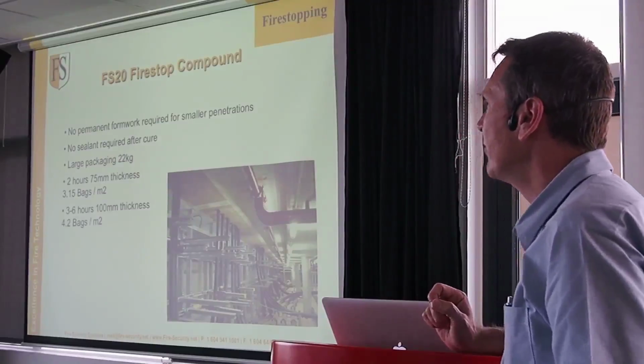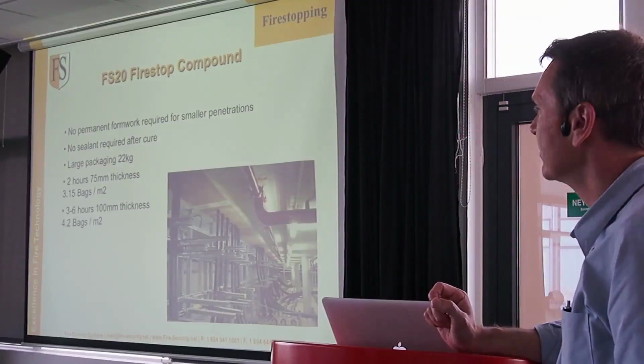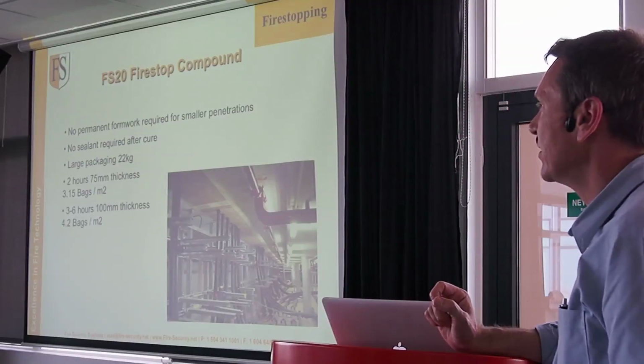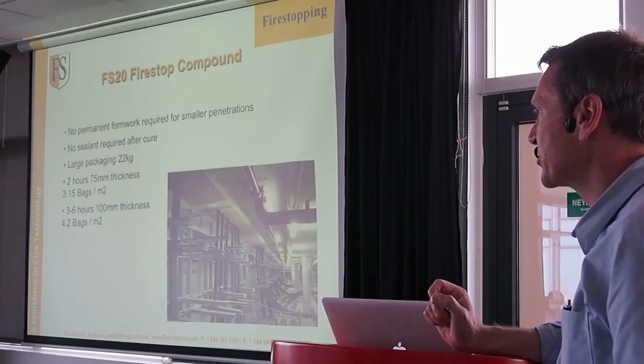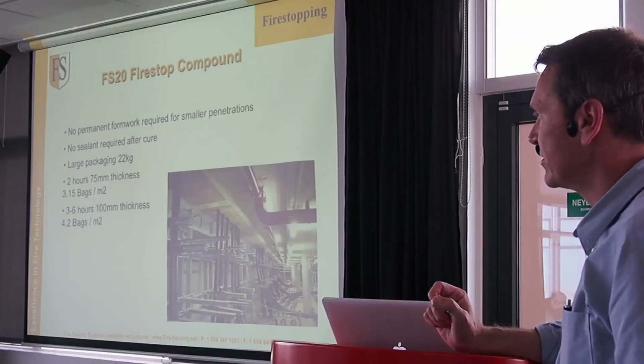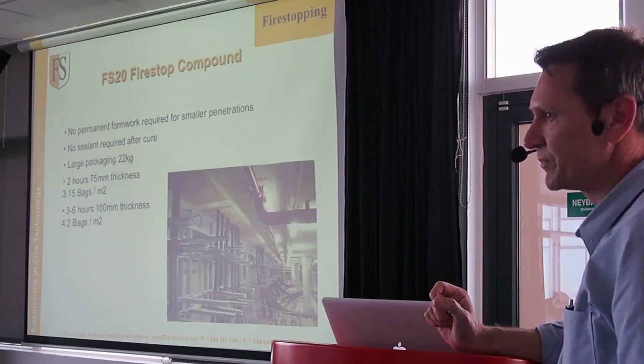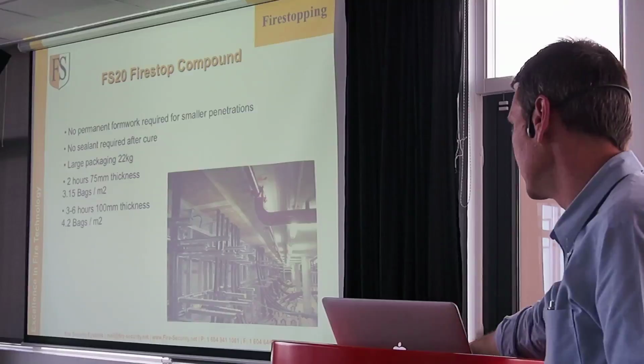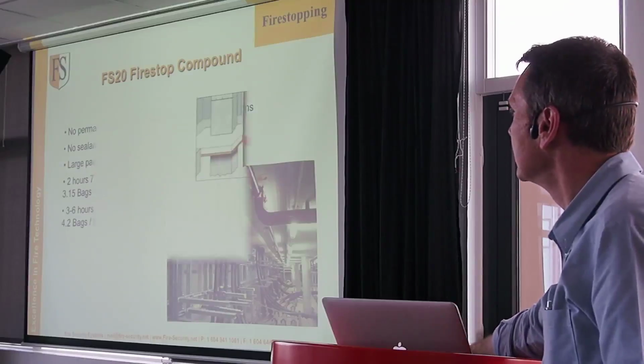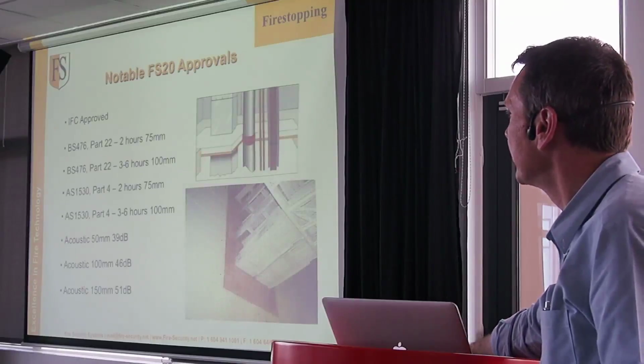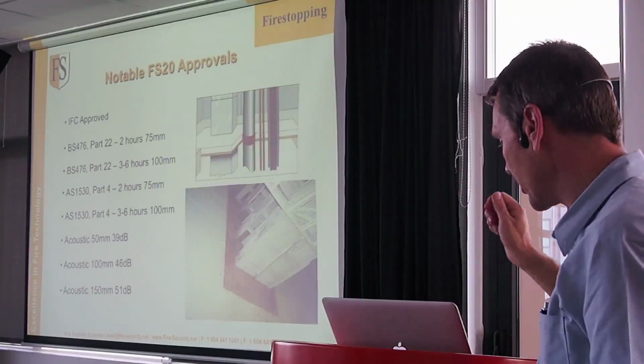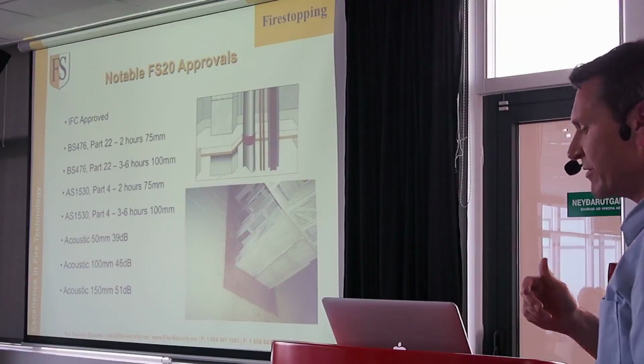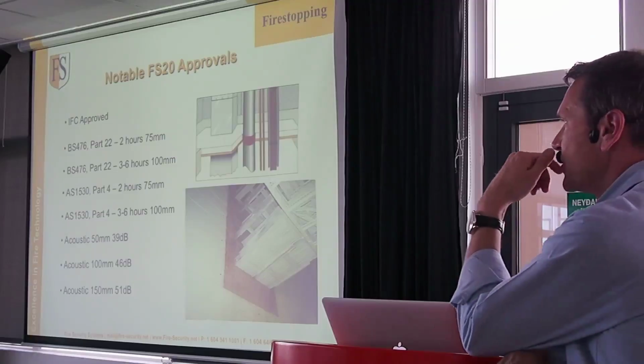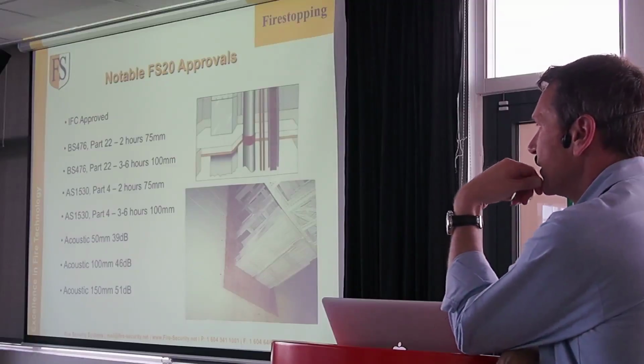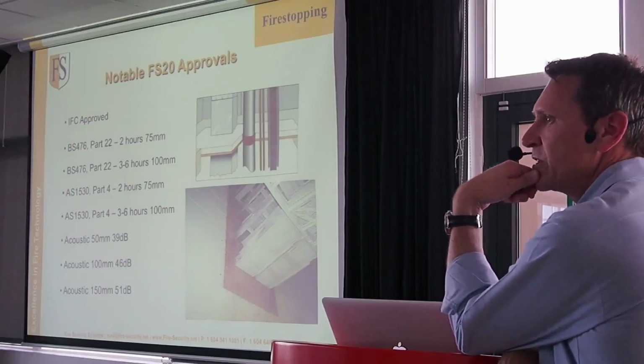And for our 2 hour fire rating, it's 75mm thickness floor or wall, which is 3.15 bags per square metre, and a 3 to 6 hour fire rating, which is 100mm thickness, is 4.2 bags. And when we look at our approvals, these products are very, very simple. Simple and effective solutions, but there's not much to them. It's a bag of mortar and it's a fire-rated bag.